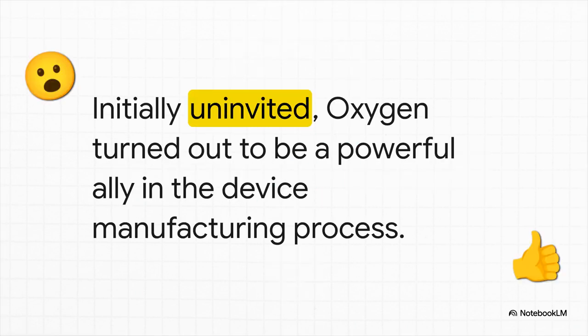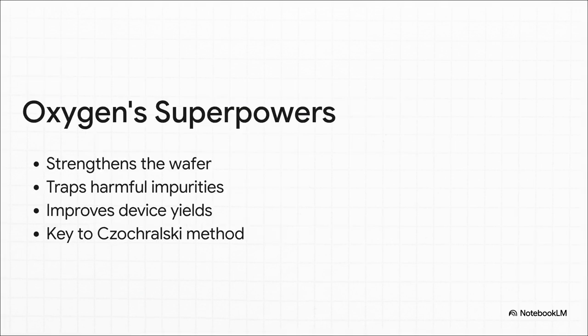That's right, oxygen. It turns out this initially uninvited guest, as the research calls it, was actually a powerful ally in disguise. Engineers found that by intentionally dissolving a tiny, tiny amount of oxygen into the silicon, we're talking like 10 to 20 parts per million, basically nothing, they could create a chip that was way more robust and reliable. So what does it actually do?